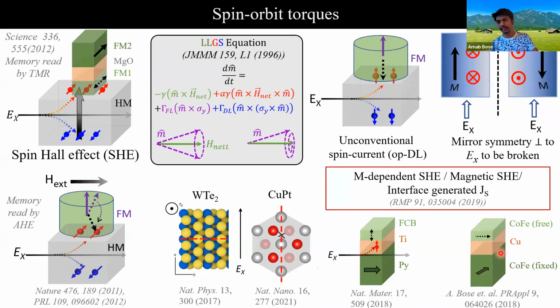In one of my experiments, we also did very similar things. We also implemented in-plane GMR, but we had both magnets in the plane. One of the magnets was pinned using the ferromagnet-antiferromagnet standard coupling. In this case, we find that when we run the in-plane electric field or in-plane current, it produces an effective out-of-plane magnetic field that causes in-plane torque on the magnet. So both these methods can be very efficient to manipulate out-of-plane spins.